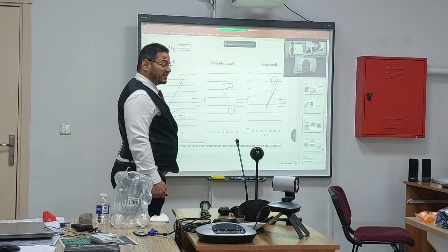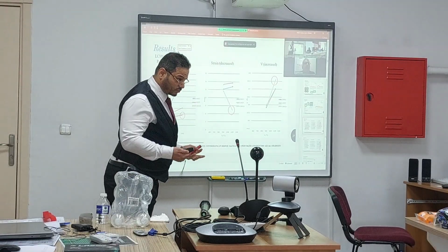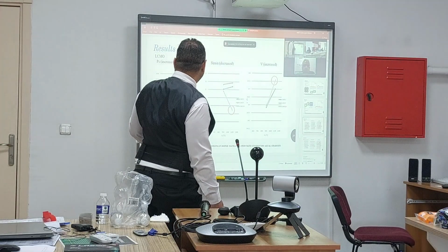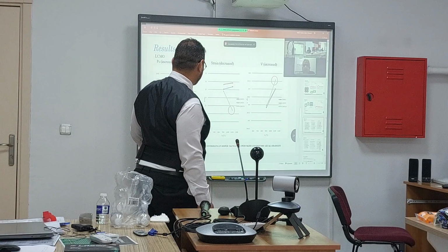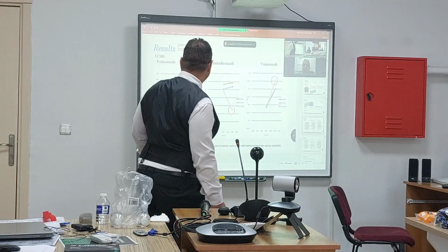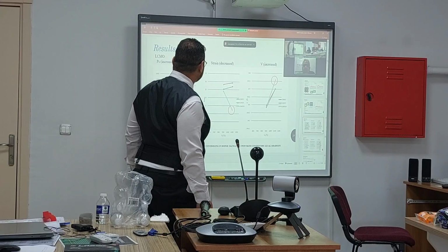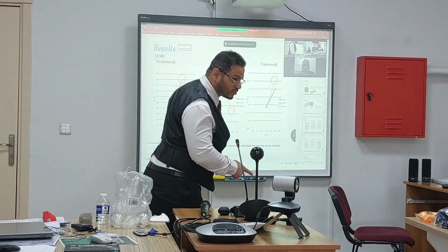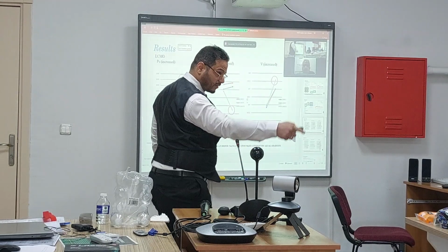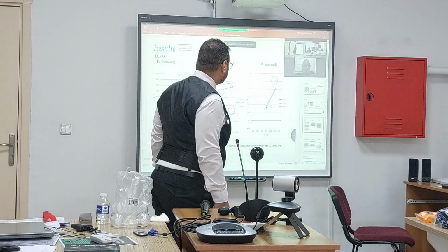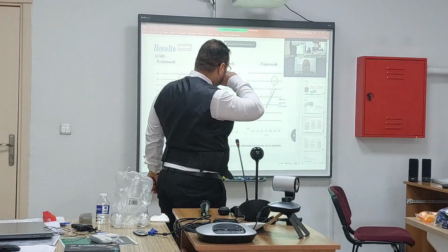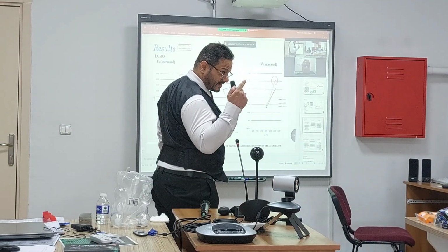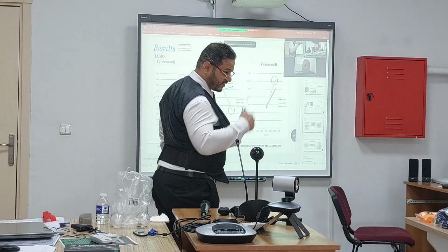By that I illustrated a summary of my results about the particle size at 1 molar ratio. It was bigger when I increased the temperature from 900 to 1100. For all of these, lanthanum calcium manganese oxide, the particle size increased, but with a different ratio, by increasing the temperature from 900 to 1100. And the unit cell volume, don't forget it, all of these increased with different ratios by increasing the temperature. Increasing the temperature is very important.